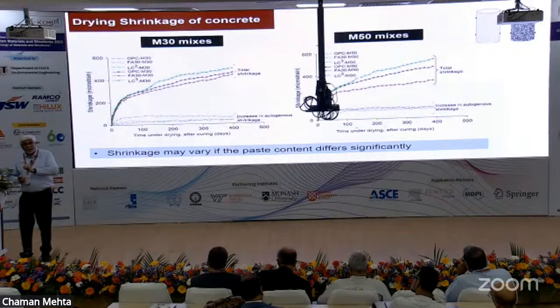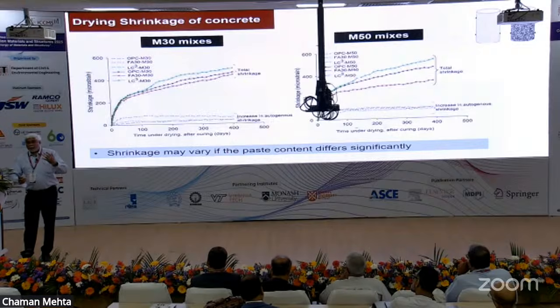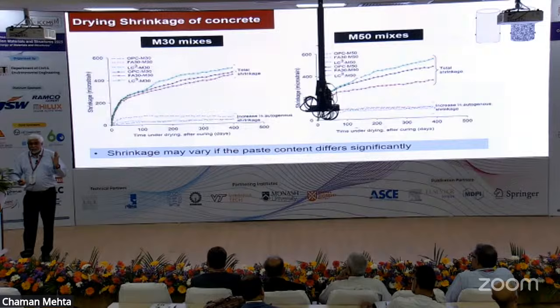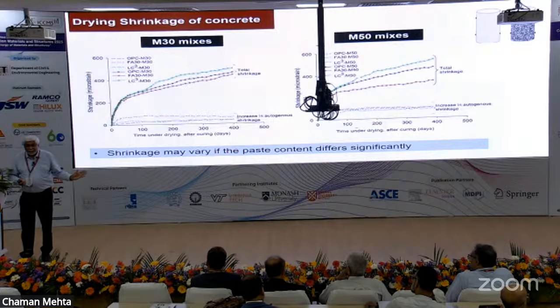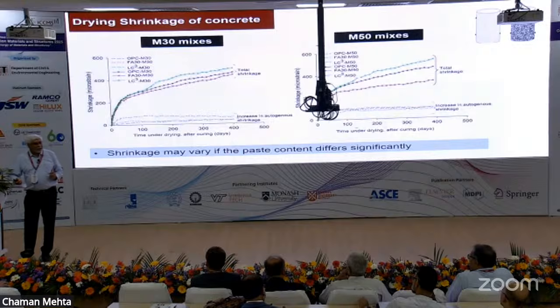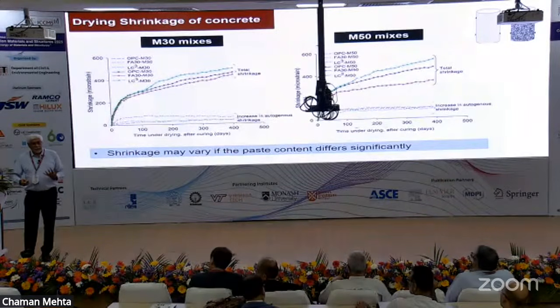And when does the shrinkage occur? Now, with a lot of tests with many concretes in India, we are finding out that shrinkage and creep stabilize in fly ash concrete after about 2-3 years, whereas it would stabilize maybe in 1 year in normal concrete. But where do you do tests? You don't have enough models. Okay, we don't have enough data. So this is something again that we have to start looking at.